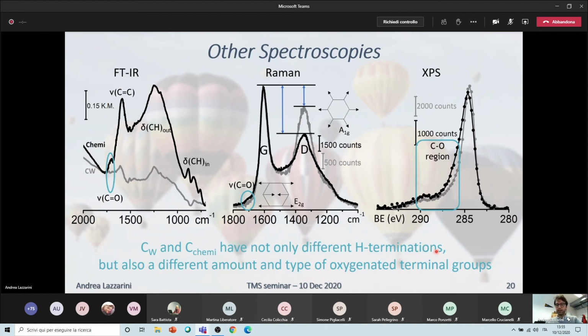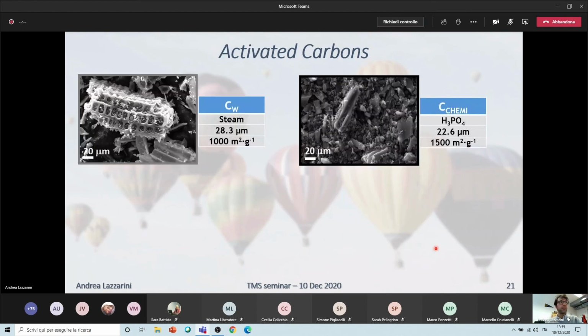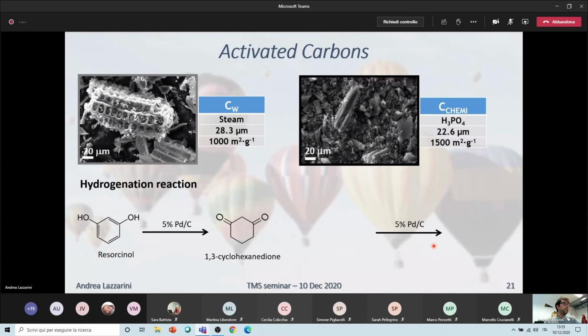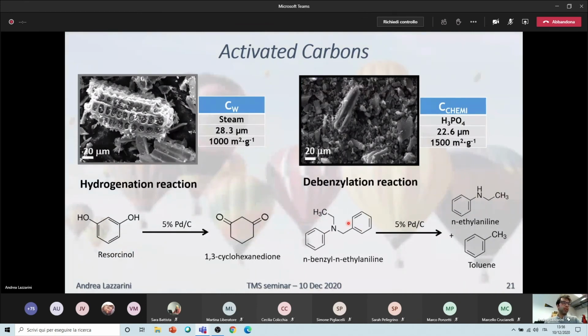So if we come back to our two carbons, we made 5% palladium on carbon catalysts on these two, and we tested them for hydrogenation reactions. While the first catalyst was very active for the hydrogenation reaction of the benzene ring, the second one was more active in the debenzylation reaction, by cutting this carbon-hydrogen bond here, carbon-nitrogen bond here.